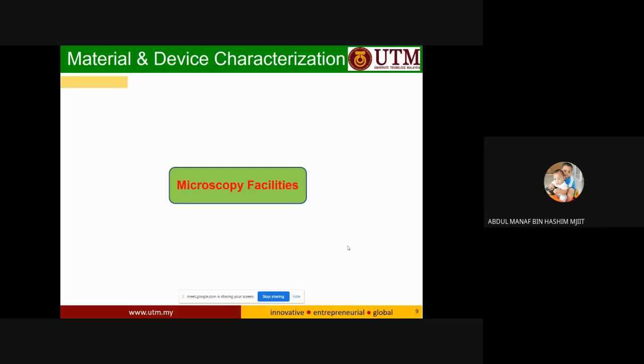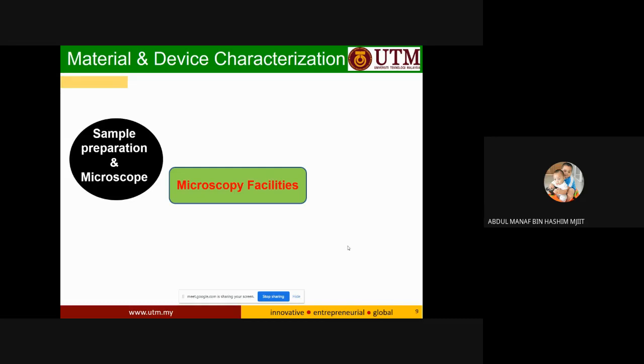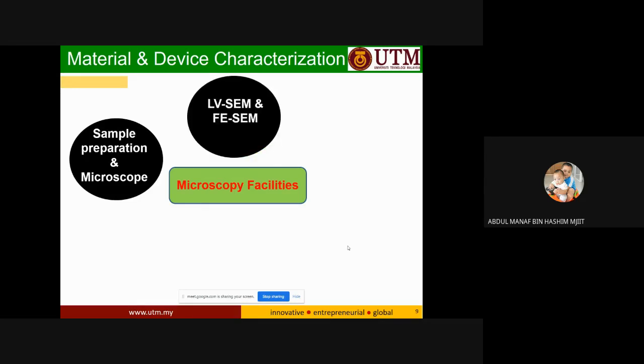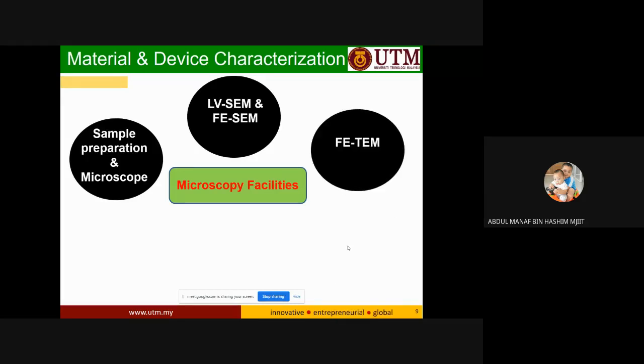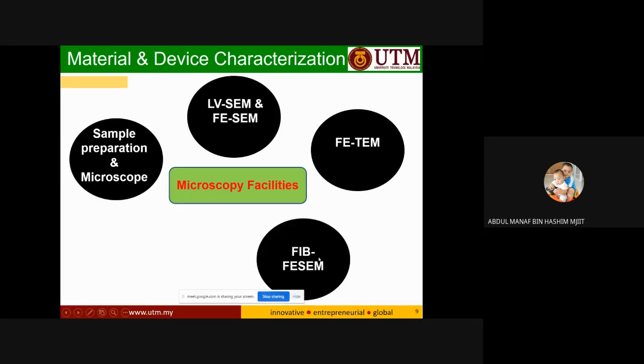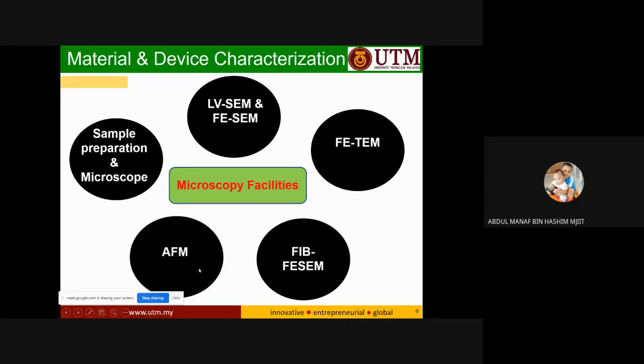Okay, so for the microscopy facility, we have sample preparation and a microscope for the sample preparation, and we also have 2 kinds of SEM, low vacuum SEM and also field emission SEM. And then we also have a TEM, transmission electron microscopy, and then we have a FIB combined with an SEM system, and then we also have AFM.